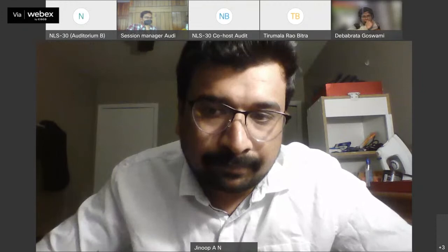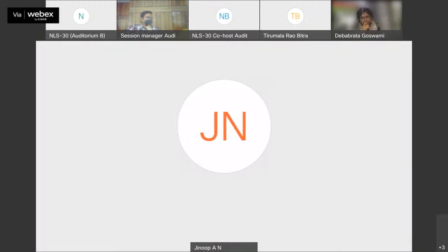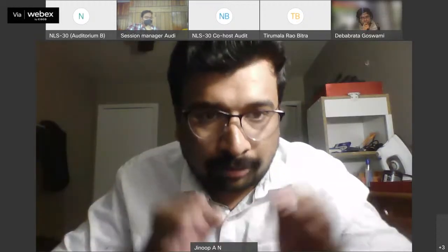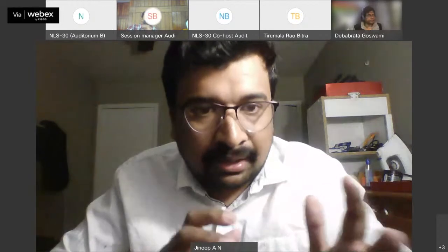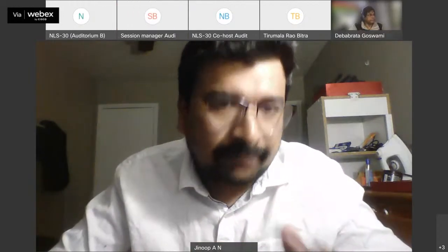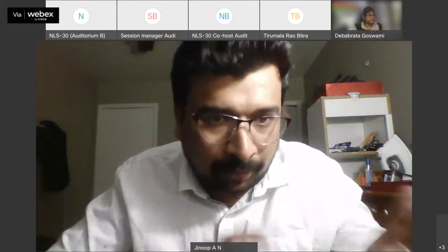Jinoop, sorry to interrupt. Can you elaborate on process window? What does it refer to? Process window refers to that zone of process parameters. Like we have different process parameters in LENS, like laser power, scanning speed, powder feed rate, and beam diameter. So we have a particular range of process parameters which can be used for the continuous deposition and defect-free deposition of a particular material.